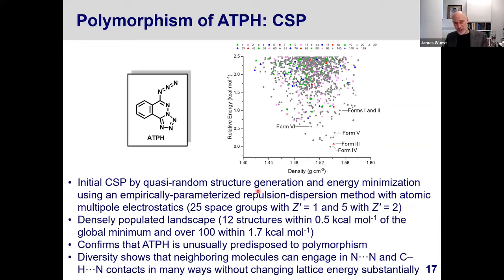This initial crystal structure prediction plot was based on a fairly straightforward force field. I describe it here a little bit, and if you're interested in the details, you can look at the eventual paper. But it's limited, just for those who have a specialist interest in this, to the 25 most common space groups with Z prime equals 1, and the 5 most common with Z prime equals 2. So it's a good look at the potential structures, but not entirely complete.